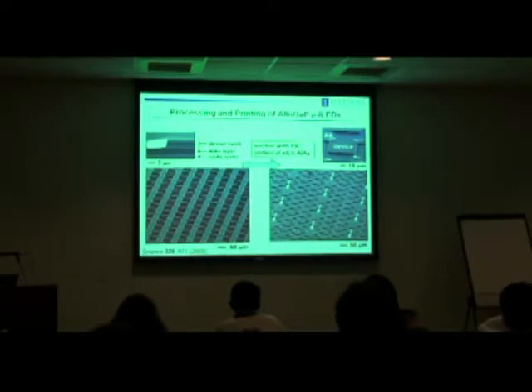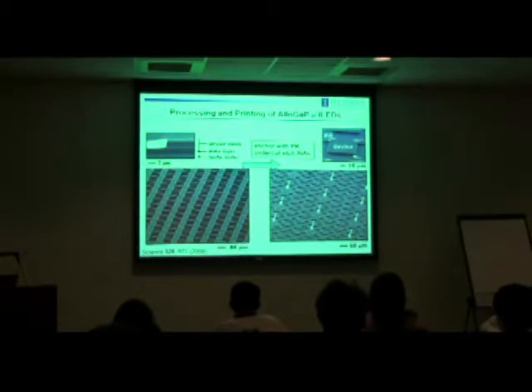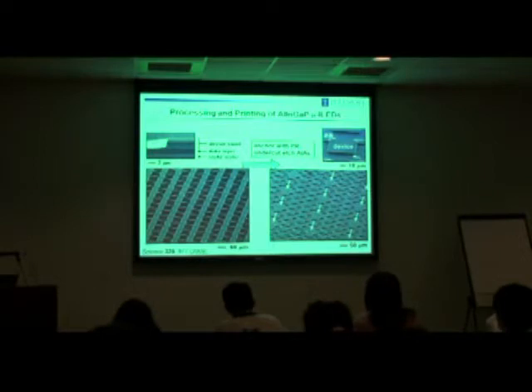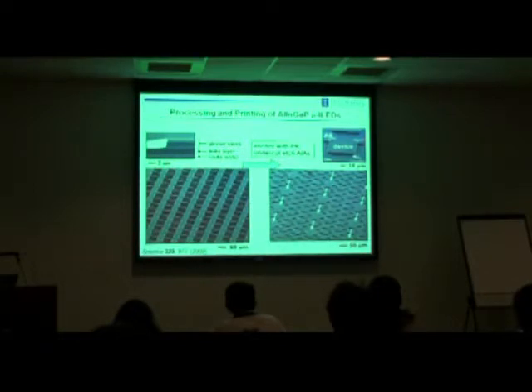So the process for building these thin LEDs involves laterally defining their geometries by vertically etching down through the active materials to expose the aluminum arsenide. Then we pattern little pieces of photoresist that anchor these devices to the underlying layer after they're completely undercut etched by immersion in HF. So these devices are in a diving board type geometry anchored at their endpoints by these photoresist anchors such that they don't lose their lithographically defined locations and simply wash off into the etching bath after eliminating this aluminum arsenide layer.